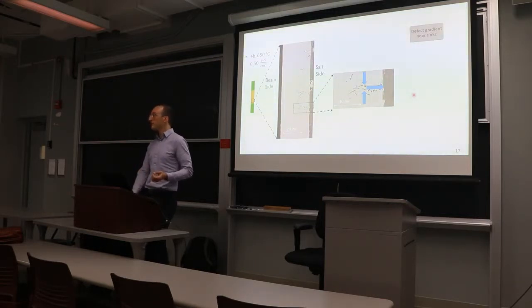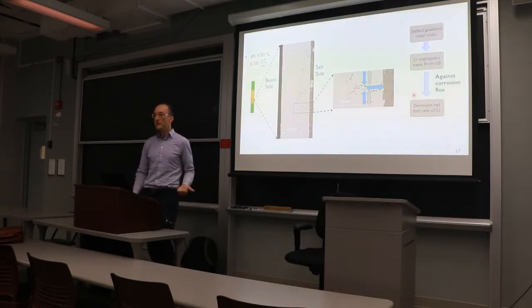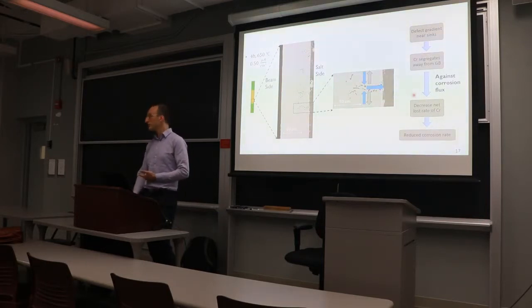So to show it a little more graphically, here is a corroded grain boundary from one of our samples, and normally chromium will move into the grain boundary, come out this superhighway, and get dissolved into the salt. And there's a defect gradient near sinks, only present with radiation, which causes a movement of chromium in the opposite way, and decreases the net loss rate of chromium, and therefore slows the corrosion rate in molten salts.